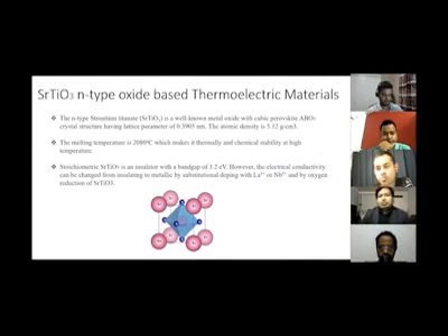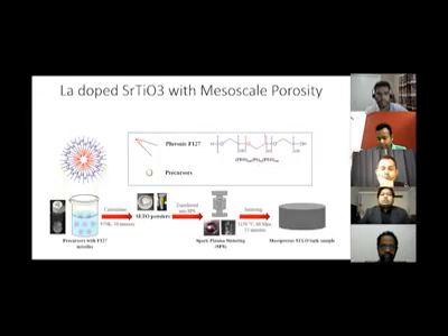Basically strontium titanate or barium titanate are insulating materials with an energy gap of 3.2 electron volt. But the beauty of this material is that we can easily make them insulating, or we can make them conducting or metallic by doping. Normally we do doping with lanthanum on the A-site, or niobium on the B-site, to make them N-type semiconducting materials. This is a very basic step to work with metal oxide. We need to make them electrically conducting first of all. So we dope with lanthanum. Here you can see the process.